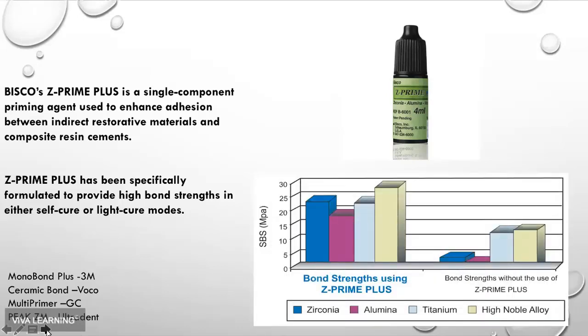But this graph shows the addition of Z Prime to the cementation process and the increase in bond strength that happens. So on the left is using Z Prime, on the right of the graph is without Z Prime. If you look at the difference in bond strength of cement to zirconia when you use Z Prime, that's the blue column on the left versus the blue column on the right, you can see there's a significant improvement in the bond strength just by adding a drop of this material to the surface.